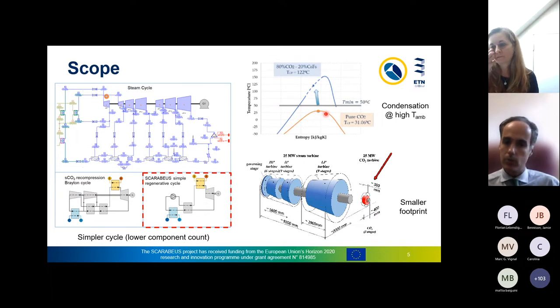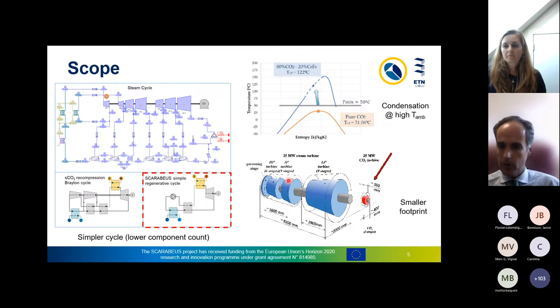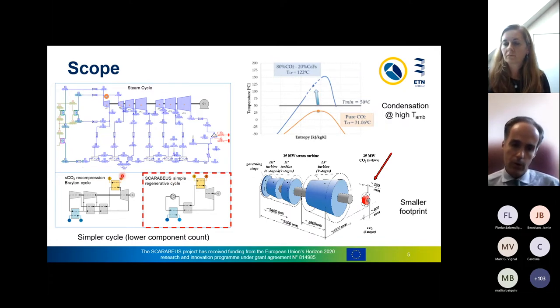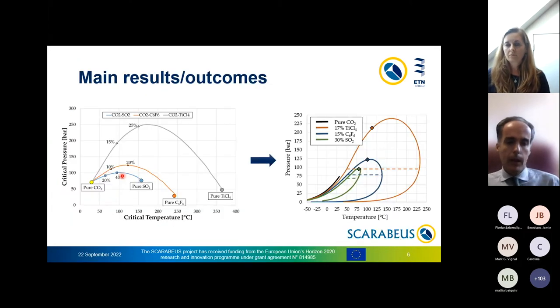This is the temperature entropy diagram, the saturation line for pure CO2. And this is for one of the reference mixtures that we are considering. If you are able to go down to 50 degrees C, then you can have condensation. Therefore, you can enhance performance. We've also mentioned that we are going to have more compact turbomachinery and less complexity in the cycle layout. Fewer components, a lower component count, translates into lower cost. So this is the way we work.